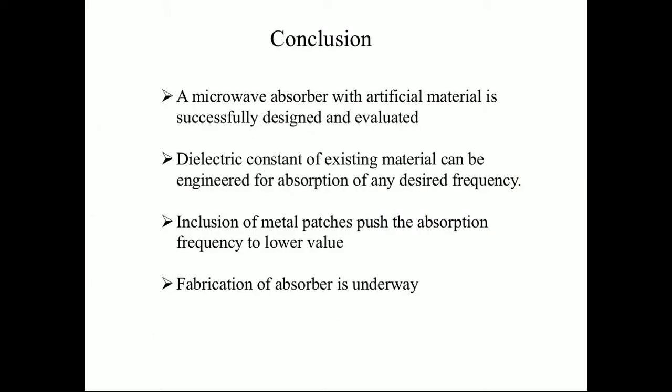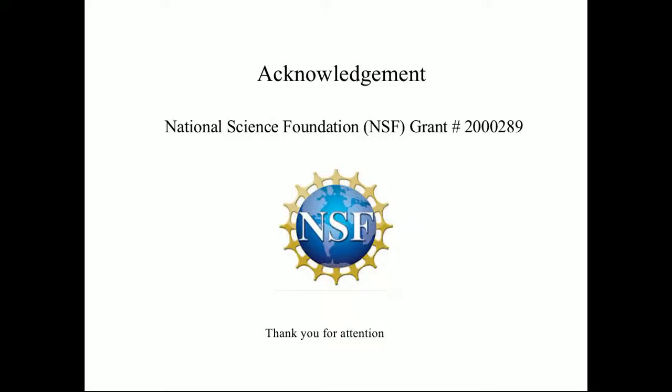In conclusion, a microwave absorber with artificial materials successfully designed and evaluated. The dielectric constant of existing material can be engineered for absorption of any desired frequency. An inclusion of metal patches push the absorption frequency to a lower value. A fabrication of absorber is underway. I would like to acknowledge the National Science Foundation and thank you for your attention.